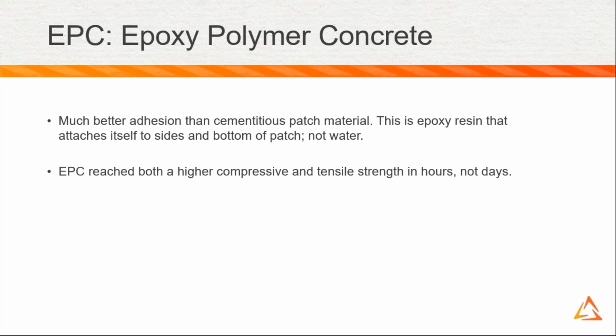EPC can reach both a high compressive strength and a high tensile strength in hours versus days. So if you've ever used an accelerated cure concrete patch in your factory and it needs to be coated, you need to wait about 7 to 10 days before you can apply a coating. With this, you need to wait about 6 to 8 hours. Once it's hard enough that you can't put a fingerprint in it, then it's ready to be coated. So it offers a lot of advantages in quicker return to service.